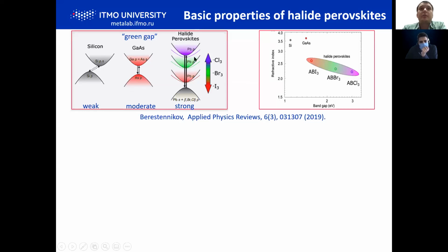Just a few words about some basic properties of halide perovskites. Of course, there are some advantages over silicon, because silicon is an indirect band gap material. The interband transition in perovskites is stronger than in gallium arsenide. Halide perovskites are easy to tune by changing the halogen from chlorine to iodine. We can gradually tune the composition and band gap from 1.5 electron volts up to approximately 3 electron volts. Halide perovskites have a refractive index more than 2 and less than 3, which is enough for strong light localization in nanoparticles and nanostructures of these materials, and enough for good contrast with a glass substrate, sapphire substrate, or many other substrates where we can deposit our nanostructures.